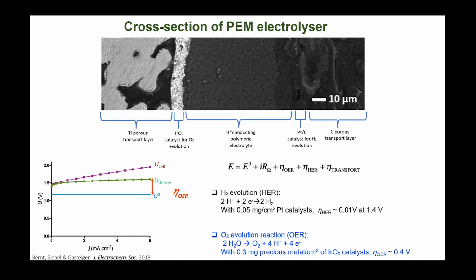Now if you look at PEM electrolyzers, you would see that you have a Nafion membrane here, and normally an iridium oxide catalyst for the oxygen evolution reaction, which is supported on a porous titanium transport layer. And on the other side, where you evolve the hydrogen, you have platinum on carbon. You would see that most inefficiencies in this process come from the oxygen evolution reaction, where you need to use quite significant amounts of iridium catalyst and you still have quite a high potential, which is not so much the case for the hydrogen evolution. You need very little platinum, in particular for PEM, so this isn't a problem.